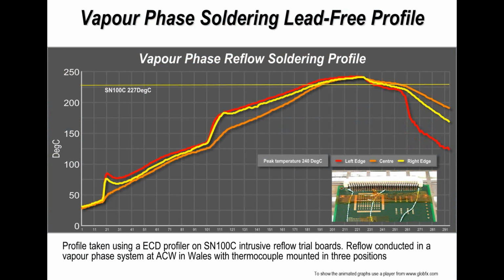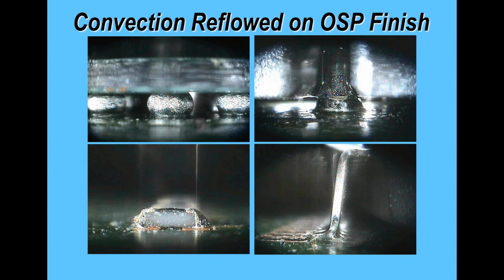And just an example of the profile. You can see the preheat, you can see the convergence of the profile monitoring positions during reflow. So don't be misled, there is always a subtle difference between temperatures on a board. If you leave it in for long enough, as you can see here, they're converging at the end of the reflow cycle. There'll still always be a subtle difference in delta T, even with vapor phase. It just depends how accurate your measuring device is.